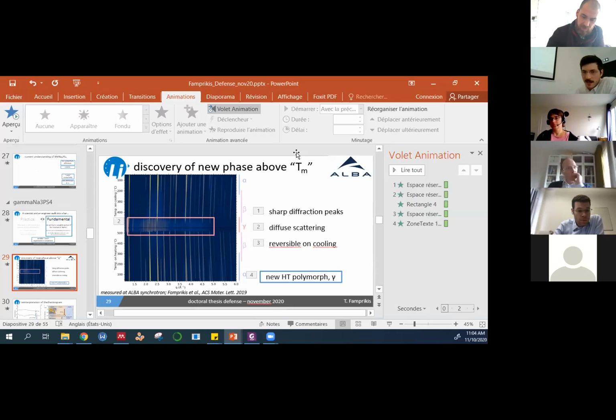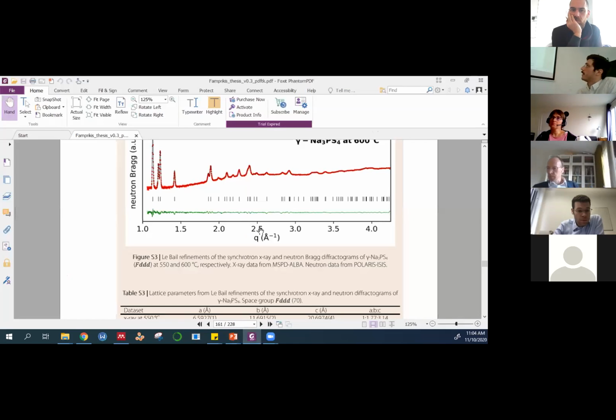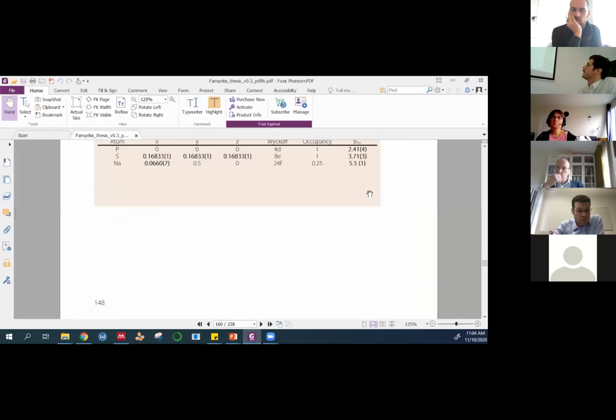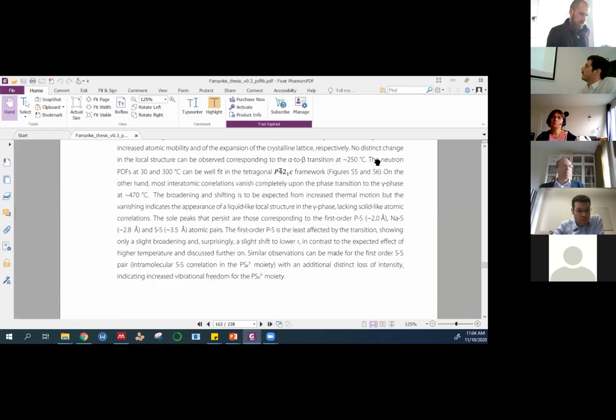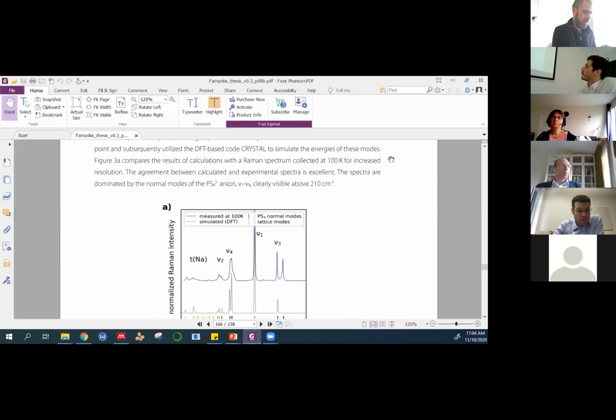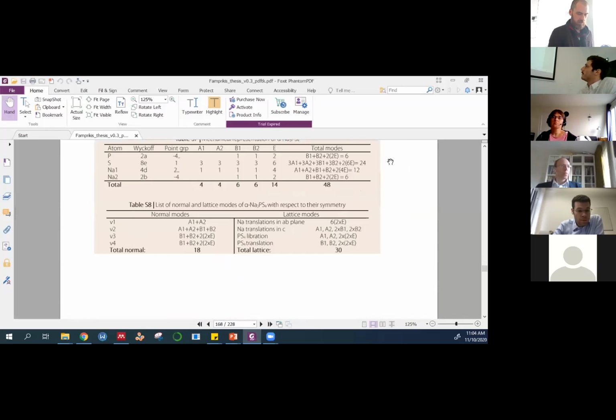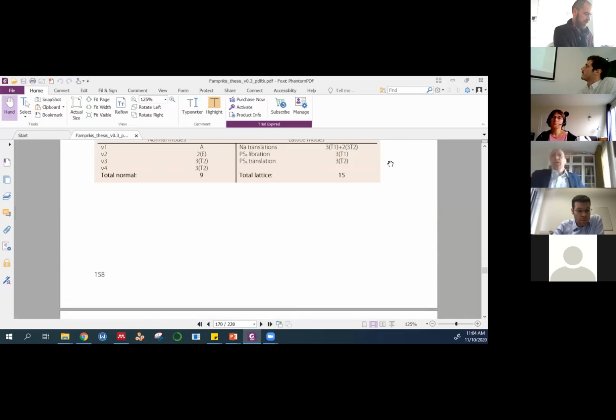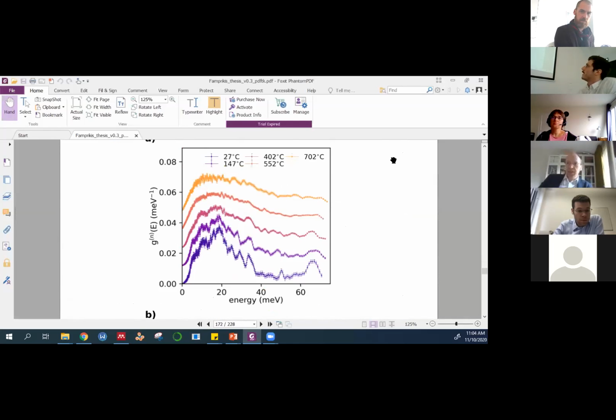Well, I think you might have noticed in my manuscript that we actually performed inelastic neutron scattering exactly with this idea in mind, to try and see the contribution of phonons to this phase. I can pull it up quickly. But what you actually see is that, similar to the PDF, the phonon spectra simply flatten out. Yeah. Right. Here. So you can see as soon as you go to the gamma phase, you basically have no features.